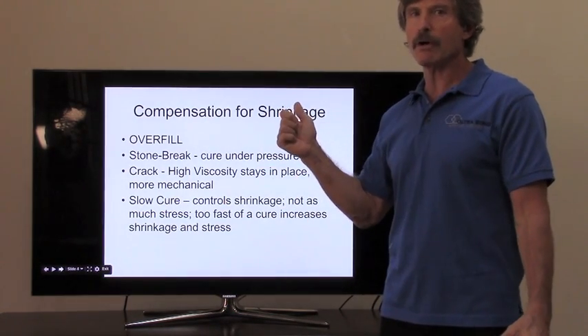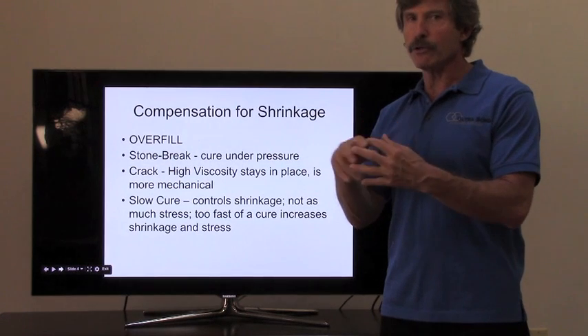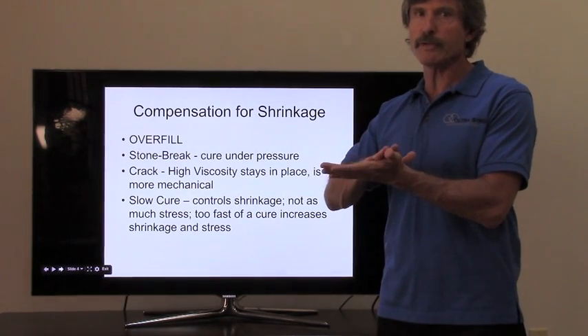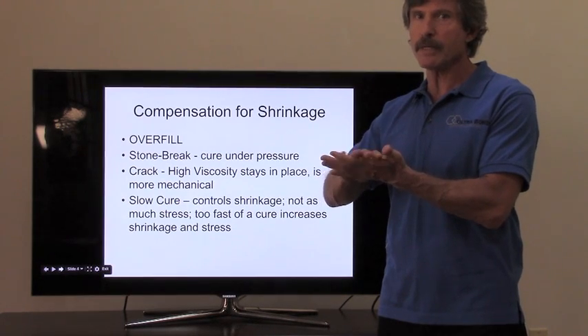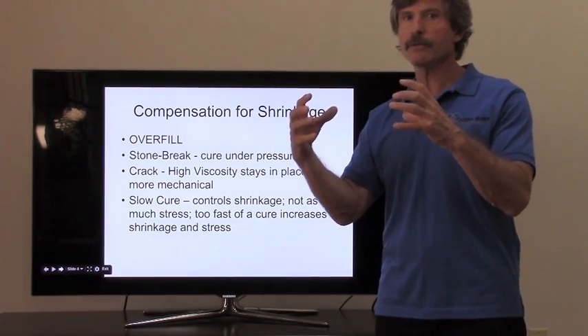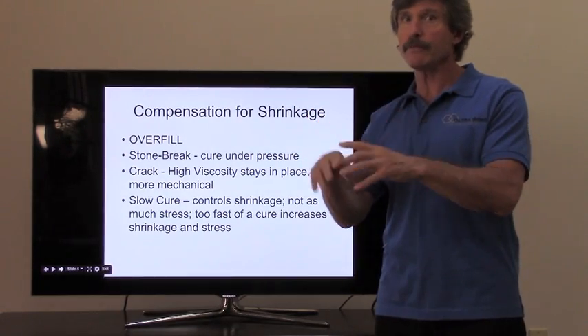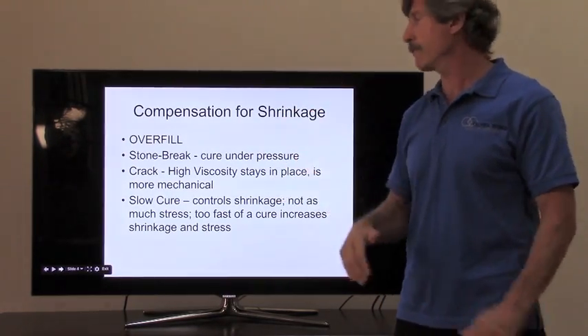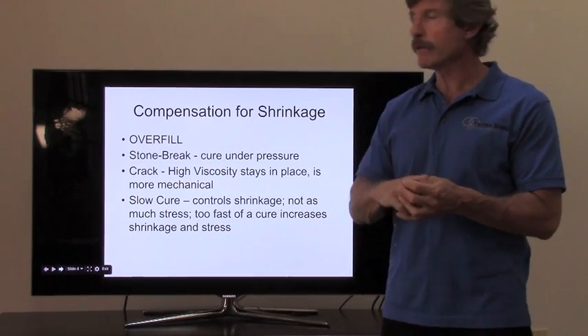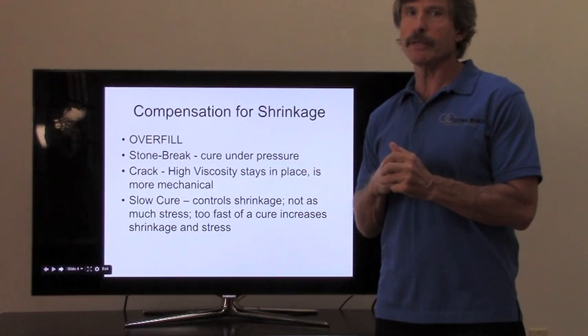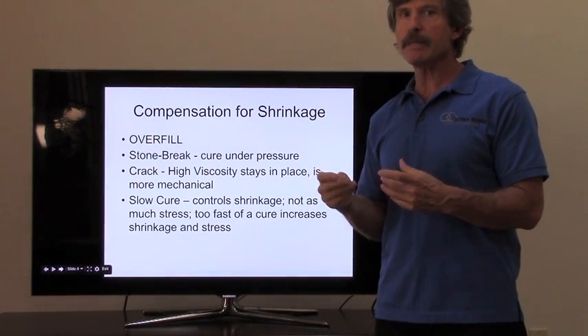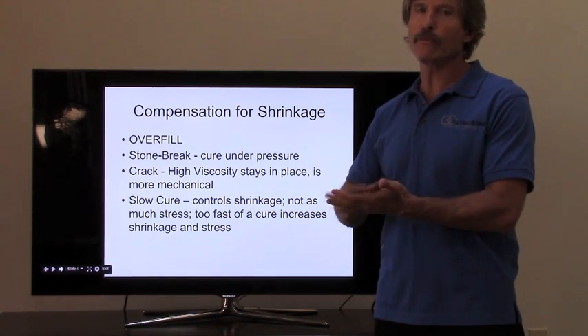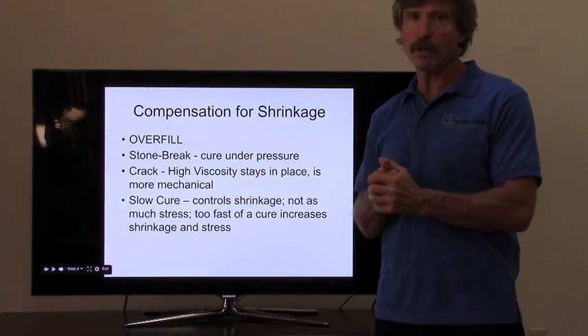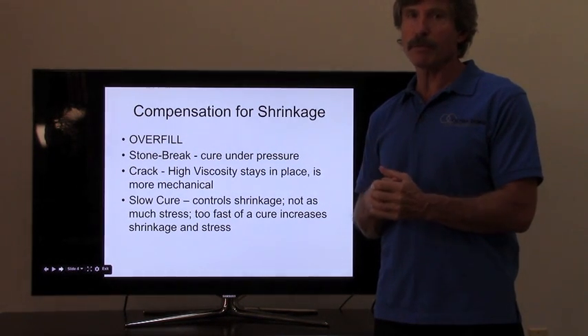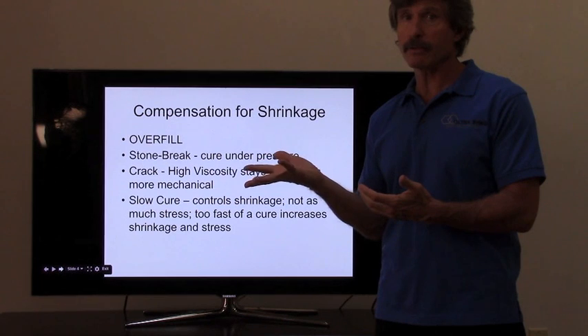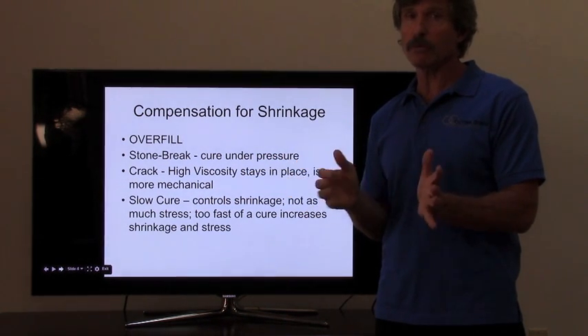If you pull your injector off, the resin is going to shrink. You might not see this right when the repair is done, but you do not have a very good bond to the PVB, and the void has less resin in it than if you had left it under pressure, because then you'll have more cured resin, more structure. What will happen is down the road, when the glass gets cold and the PVB turns hard, it'll start to separate even more from the resin, and especially in an ungaraged vehicle, your repair will look like it's not repaired. It can still be partially bonded to the glass, but it'll be off the PVB and it will look horrible.